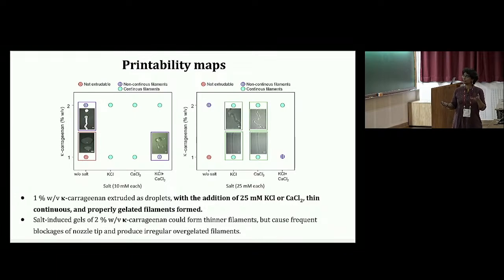So we could see that only at certain compositions, which is the potassium chloride and the calcium chloride, we could see nice long smooth filaments, and we then started to focus on these two inks, as we would say, which one of them would give me the final best print fidelity in terms of printed structure, filament width, and so on and so forth.